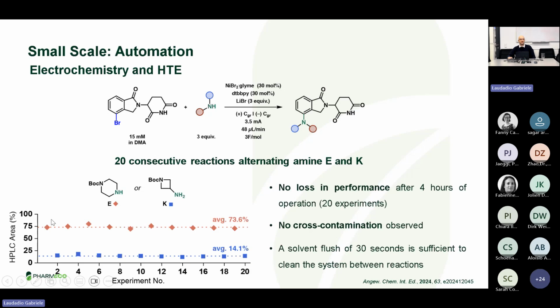And we tried the system up and down continuously for 20 times. And we could observe that the system was holding very well. There was no cross-contamination, and the average yield was almost the same over time. So there was no electrode passivation.